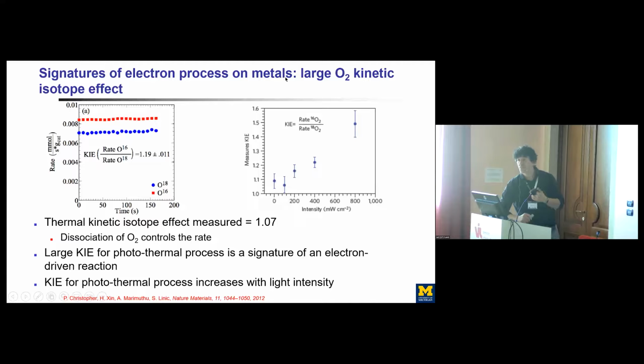Another slate of experiments is to perform kinetic isotope labeling studies. It's been known, going all the way back to Ertl and to some theory work, that the signature of an electron-driven reaction on a metal surface is that the kinetic isotope effect can be different or larger compared to the kinetic isotope effect experienced in a thermal process. So here what we do is we run an oxidation reaction, basically monitoring the rate of oxygen dissociation in a thermal process. We switch O16 to O18 and we monitor the reaction rate. When you make that switch, you go from a lighter isotope to a heavier isotope. So under thermal conditions, using transition state theory, you would expect a certain change in the reaction rate, and we measure exactly what we expect, which is about 1.07 under these temperature conditions.